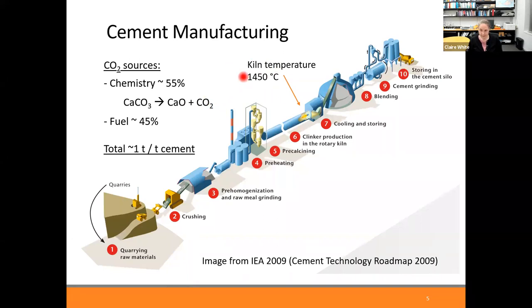The reason why we go to higher temperatures is for the formation of calcium silicate phases that are reactive with water. So we have to go to these really high temperatures to get the right phase composition in the cement powder for it to be able to react with water. And so if you look at the fuels that are used to get to these really high temperatures, such as petroleum coke, the burning of those contributes about 45% of the CO2 emissions. And then this decomposition of the limestone contributes about 55% of the emissions, such that if you look at 1 ton of the cement powder that's produced out of the plant, you're getting about a ton of CO2. So this is not insignificant in terms of the CO2 that's been generated.